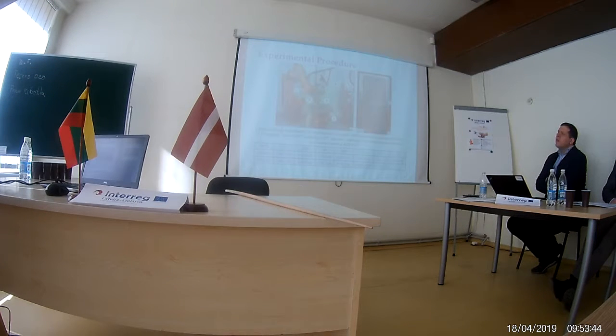So experimental work was carried out using a precise laser cladding system, which consists of an industrial robot and a 1 kilowatt ytterbium fiber laser. Experimental coatings were created on tool steel substrate D2 using high-speed steel powder M2. The properties of the created coatings were evaluated in the course of comparative analysis by examination of morphology of coating cross sections, elemental composition, micro-hardness distribution inside coatings, and tribological tests.